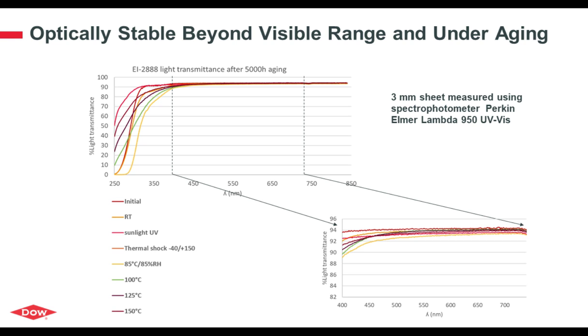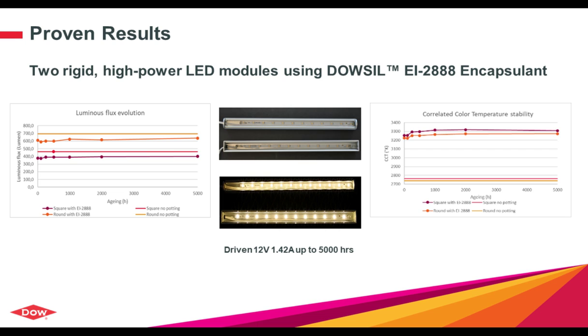But compared to those, we build adhesion at room temperature, and for the majority of applications, the running temperature that we have validated is generally lower than 150. We are most of the time talking about 100 to 120 degrees, and the optical performance remains exceptional in those ranges, and nothing to compare with urethane-type products.